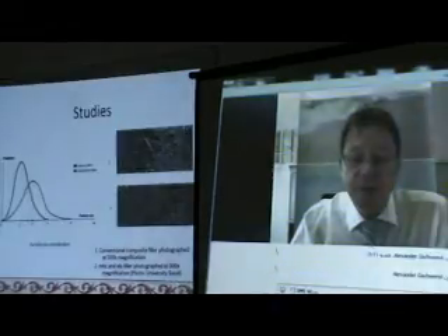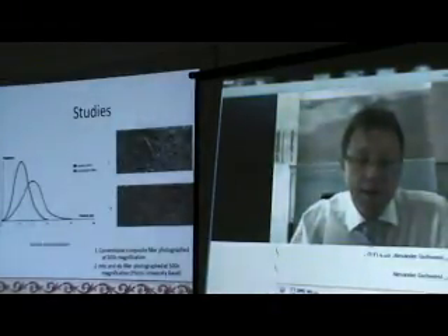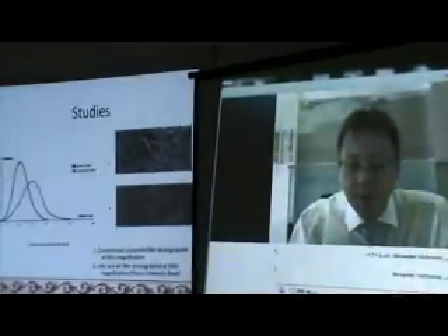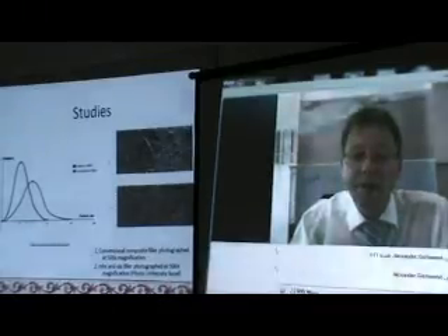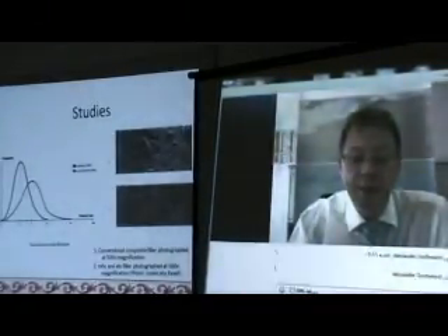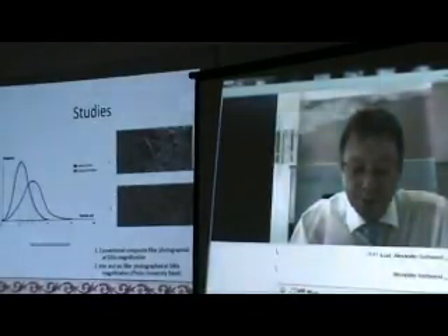Now, when you have a product like this, it means when you do polishing, there is a risk that these big particles will be taken away during the polishing. There can be small micro holes in the product and on the surface where bacteria can attach. Or later there can be discoloration and so on, bacteria which can attach to the surface.